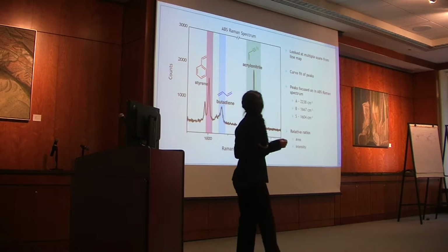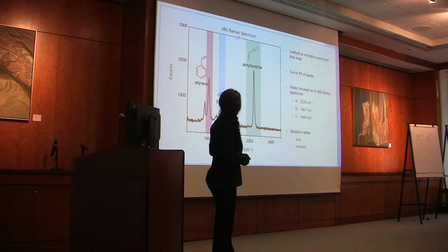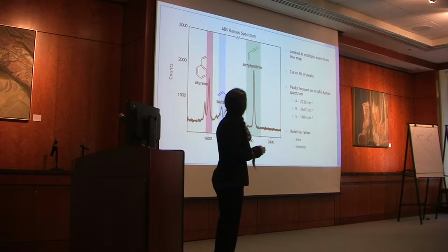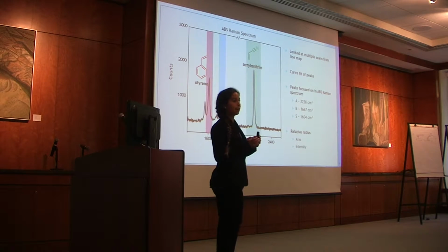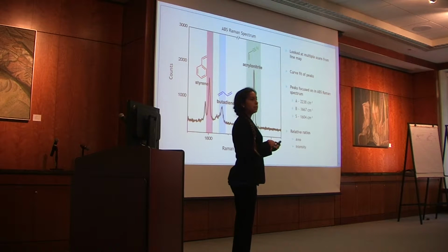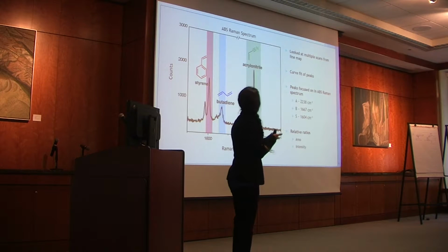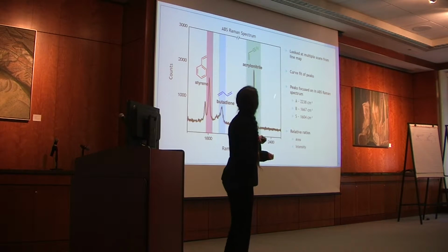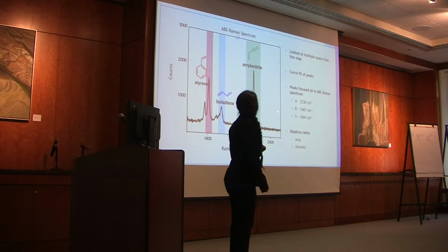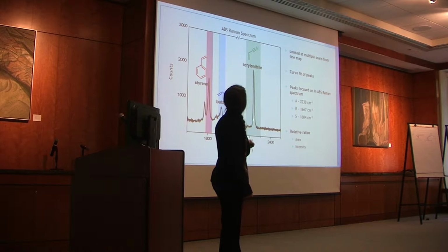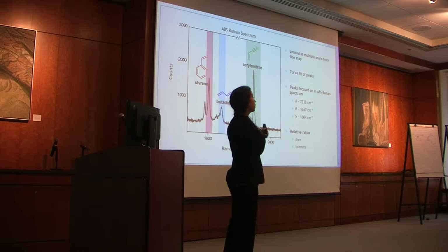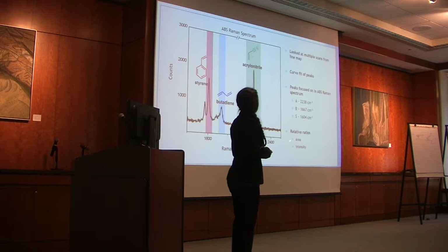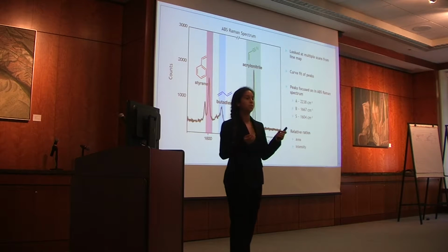So, what does a Raman spectrum look like, you may ask? This is a Raman shift versus an arbitrary intensity. And so these are peaks that were of interest with my ABS sample. We did multiple scans of a line map. Like I said in the terminology, we did line maps of different areas. We then did curve fitting of the peaks of interest. It was a Voigt curve, which is a mix of Gaussian and Lorentzian, I learned this summer. And we looked at these peaks in particular. This is an acrylonitrile peak, which is the A, butadiene, which is the B, and styrene, which is the S. And these peaks were also looked at in the previously published work. With this, I did relative ratios of area under the curves and intensity of the curves to compare this and see how homogeneity looked within these samples.